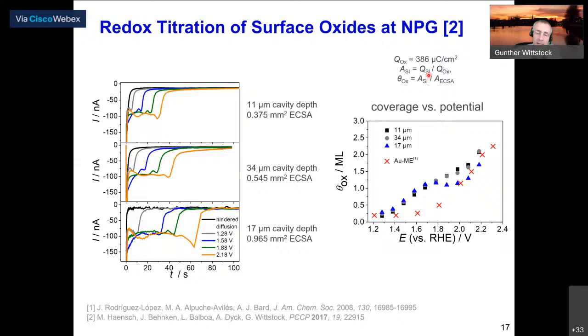Okay, so we can then determine the oxide for each of these pulse experiments, divided by the specific charge for a surface oxide on gold to obtain an area obtained in the surface interrogation mode, accessible with a certain mediator and a certain potential. And we can divide that by the electrochemical surface area, which we determine from the reduction of the surface gold oxides in an initial scan. And then we can determine the coverage with the oxides at a given potential.